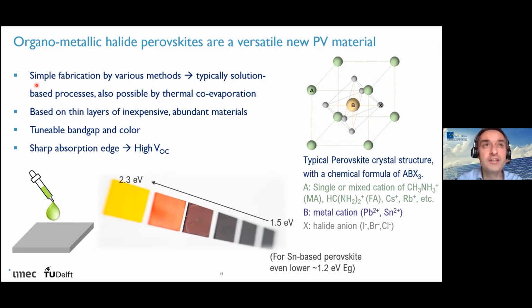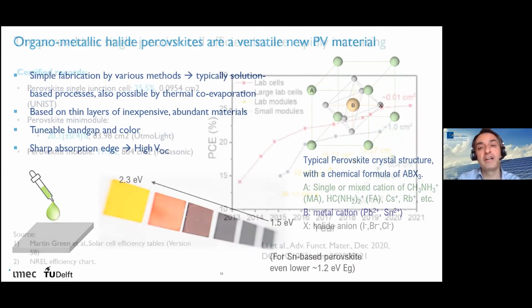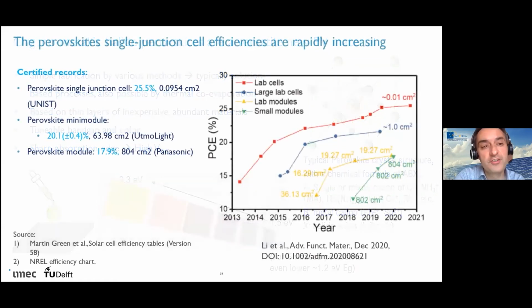You also only need a few hundred nanometers, and they have a tunable band gap. You can really tune the band gap, and that's good because we need a band gap for the top cell of around 1.7 eV. Especially why they have attracted so much attention is that in a single junction on their own, you can really reach very high efficiency. The record at the moment is 25.5%.